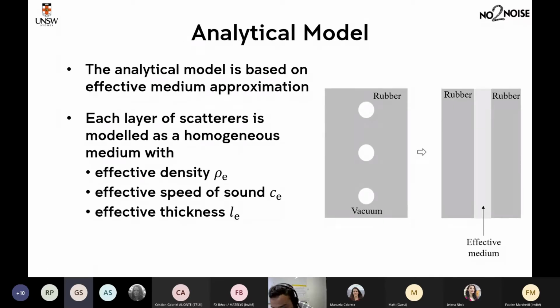So in my group here, we developed analytical and numerical models to study these acoustic coatings. The analytical model is generally based on effective medium approximation theory or homogenization theory. So what we do here is we approximate this complex media, our coating, where we have our soft rubber medium, and in that we have cavities. We approximate this system as a three-layered media. So we have rubber on either side, and in between we approximate the layer of cavities as an effective medium. For this effective medium, we have effective density, effective speed of sound, and effective thickness, right?